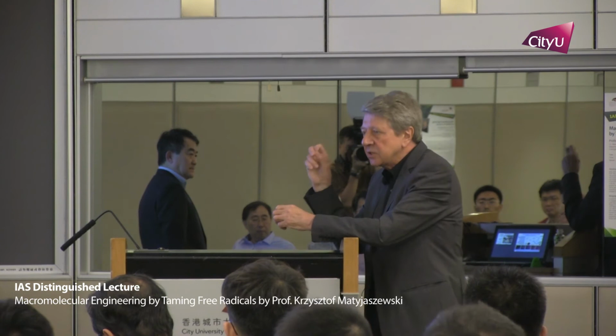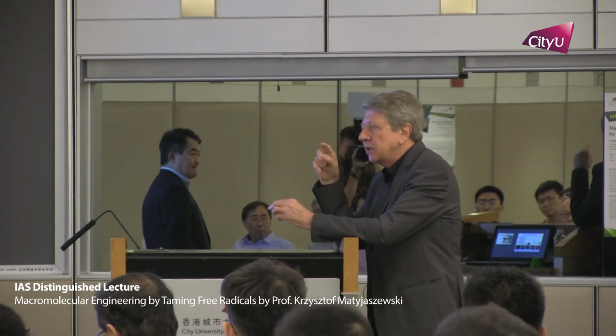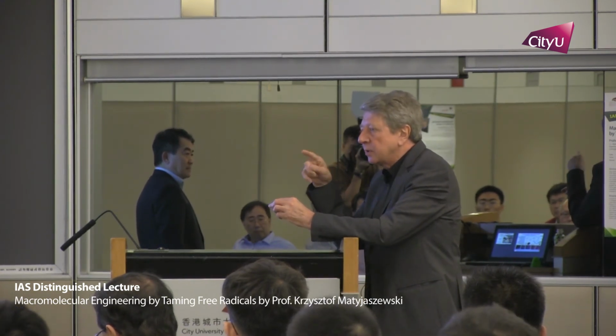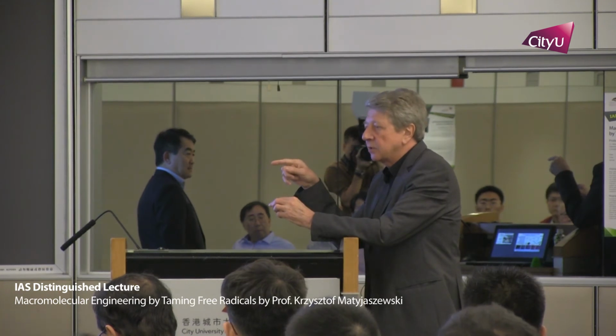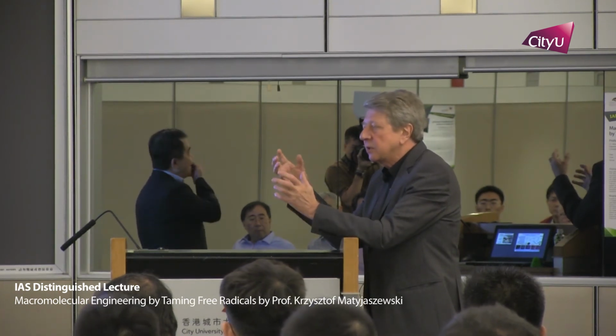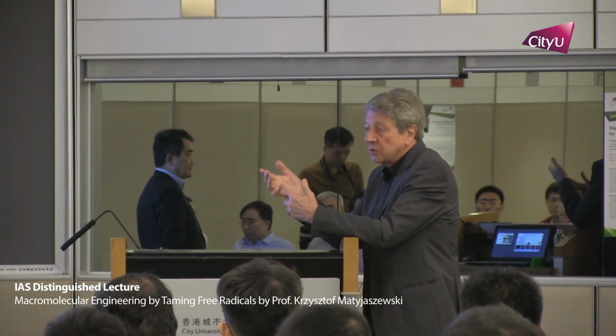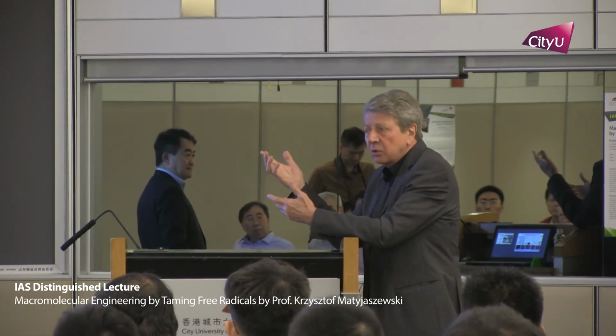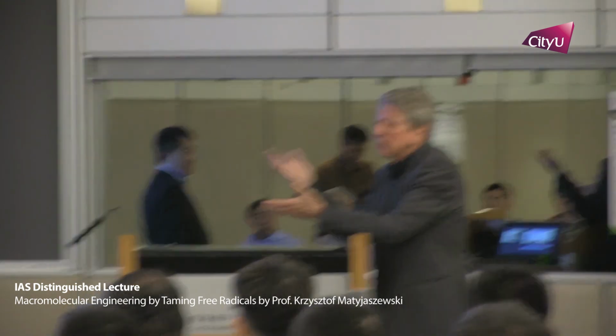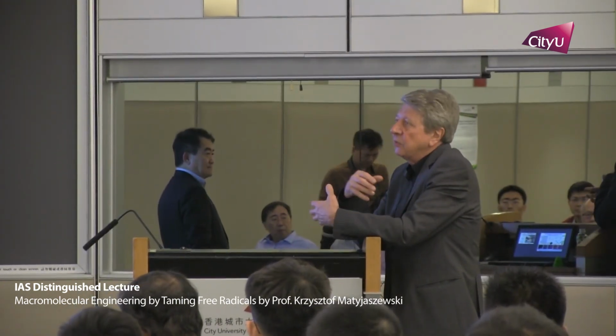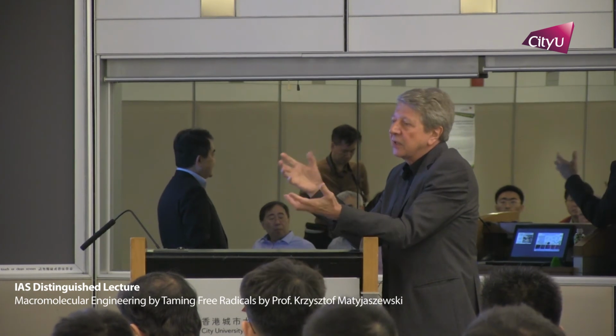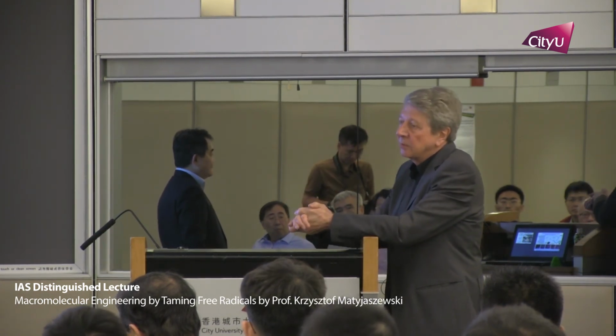So for all of these systems, for control, it's really how many times you propagate before you deactivate. Because it's a bimolecular reaction, it will be a question of concentration of the activator, so we cannot go below 1 part per million moles. Because even if reactivity would be much higher, they cannot diffuse fast enough. Okay. Thank you.